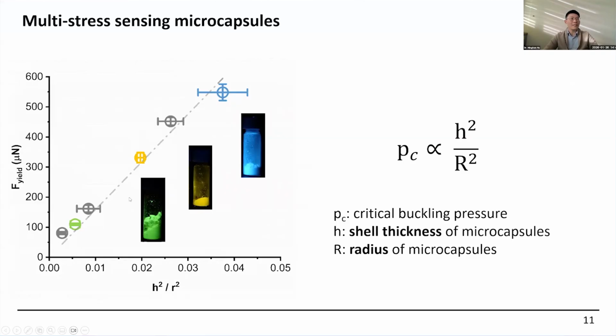We tested our microcapsules with different shell thicknesses and diameters. And we can nicely see that the breaking force can be tuned by changing the ratio between the shell thickness and the radius. Thanks to the help of Professor Bao's group, we have very nice fluorescent dyes with different emission wavelengths. Then we select three different microcapsules with different breaking forces, encapsulating the dyes inside to make microcapsules for different stress sensing.